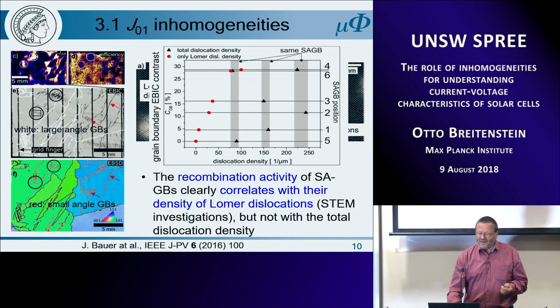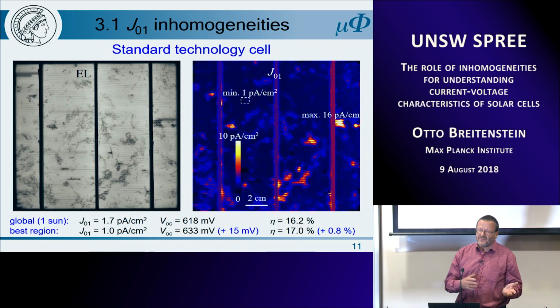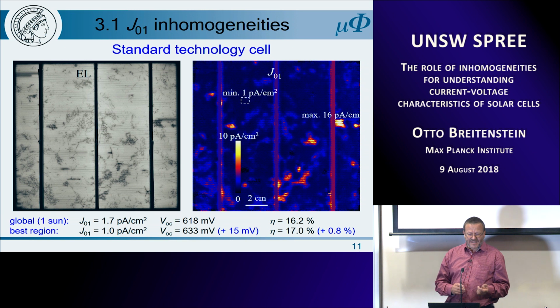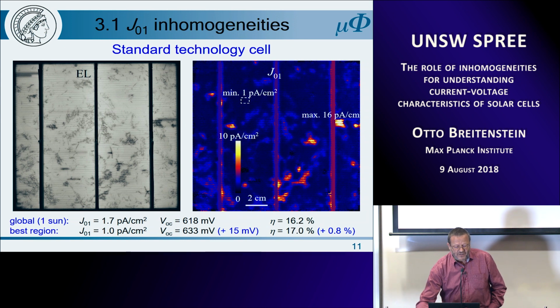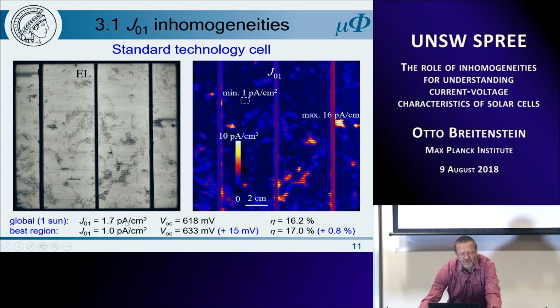Okay, now what do these low lifetime regions, which we now know where they come from, mean for the solar cell? Under one sun, this is a standard technology cell, and we have a global J01 of 1.7 picoamps, and in the best region we have 1.0 picoamps. And this is the measured and also the simulated open circuit voltage, and this is the efficiency. And in the best regions outside of these dislocated regions, we expect a much higher open circuit voltage, plus 15 millivolts, leading to an efficiency of plus 0.8% absolute.